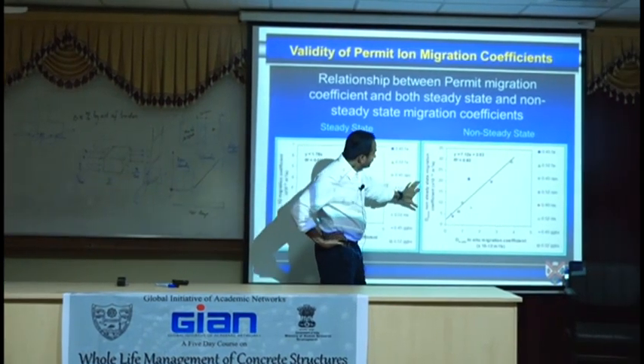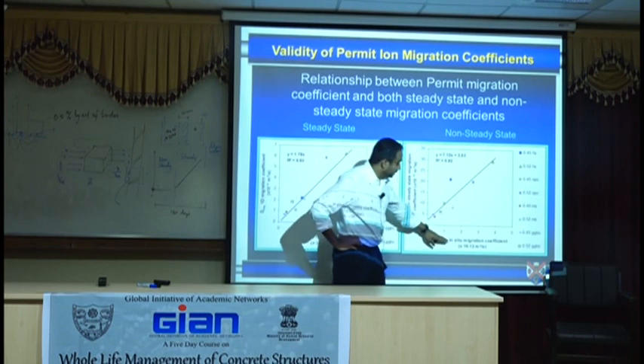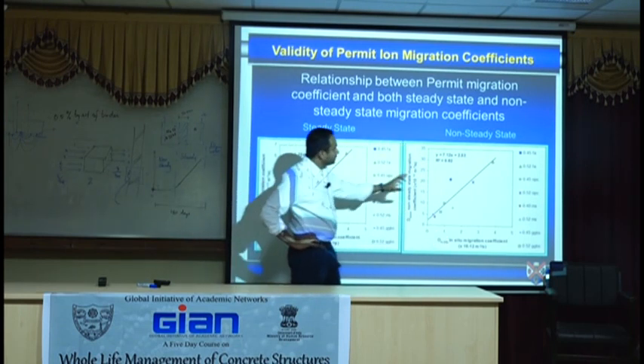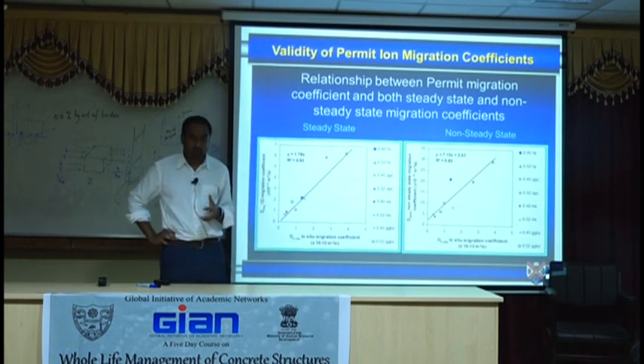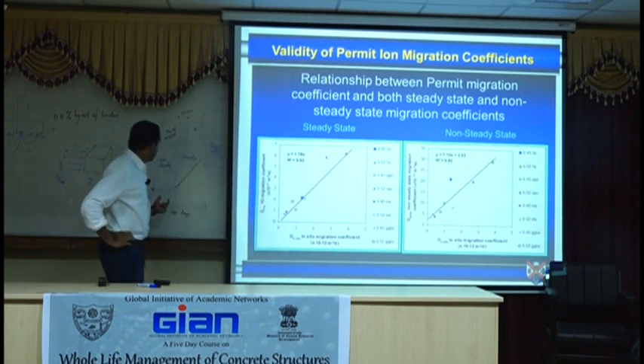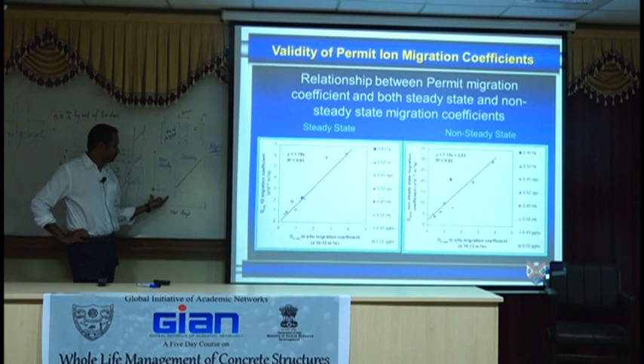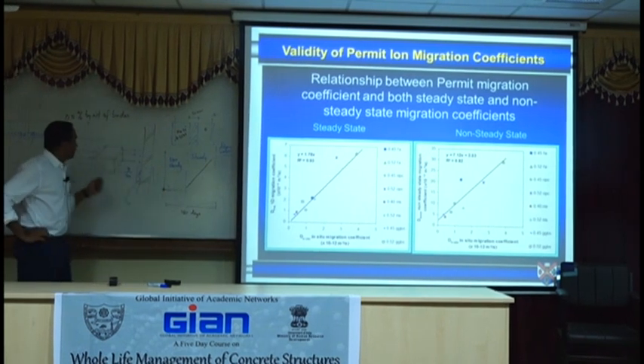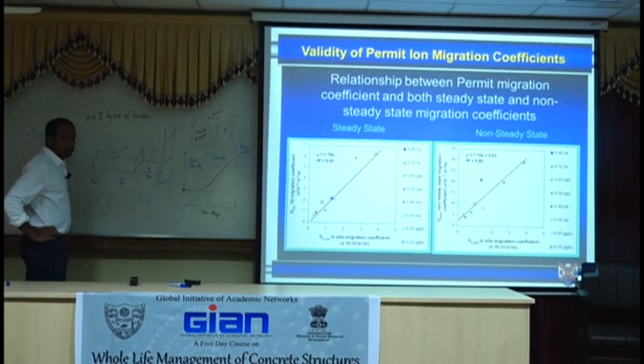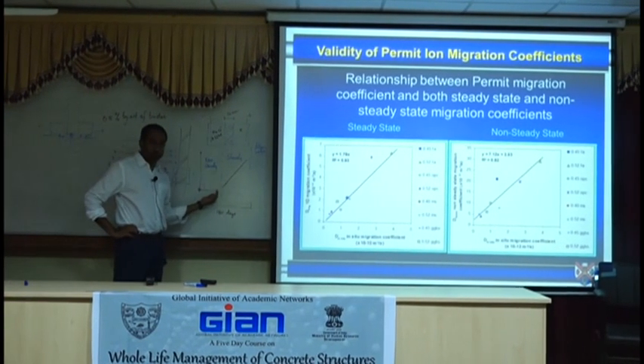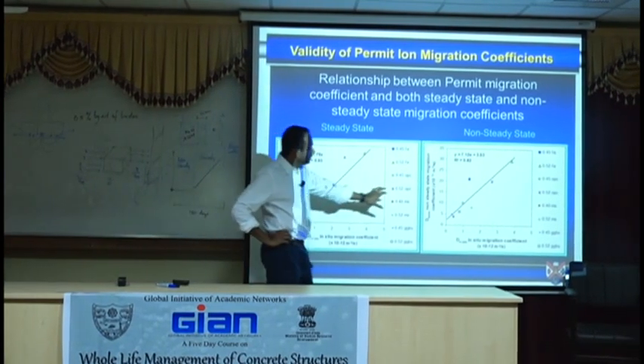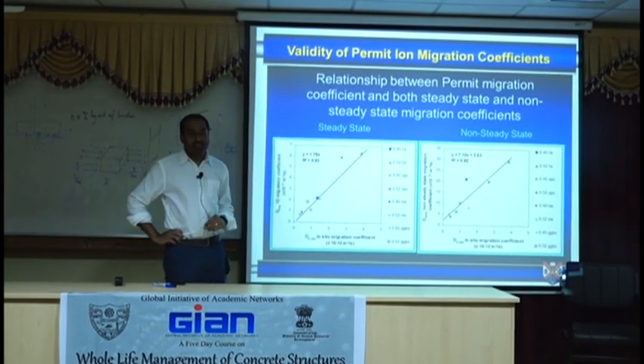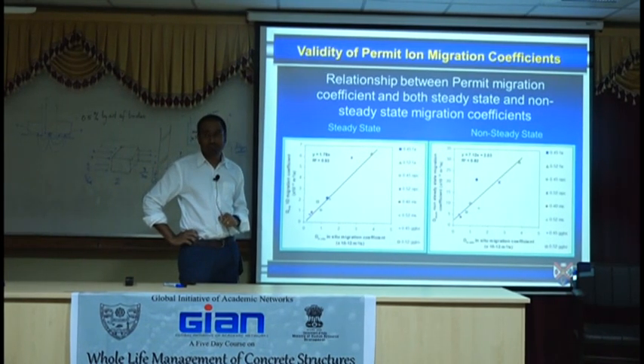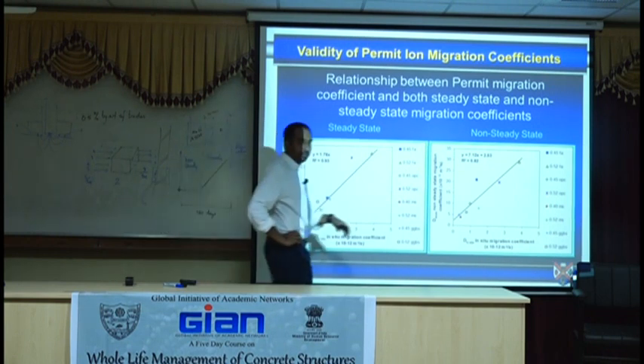Now, moving over, we looked at the comparison between non-steady state test and the permit that we've developed, and we can still see there's a stronger correlation. Okay. That can only happen due to two factors. One is that permit is measuring in this region, which it's not. It's definitely not measuring in this region, but it might be measuring the flow coming back at different times. So it could be a pseudo region somewhere here. Second, what's commercially available as a non-steady test may not necessarily be a non-steady test. Okay. We've left it at that because I didn't want to challenge this one.